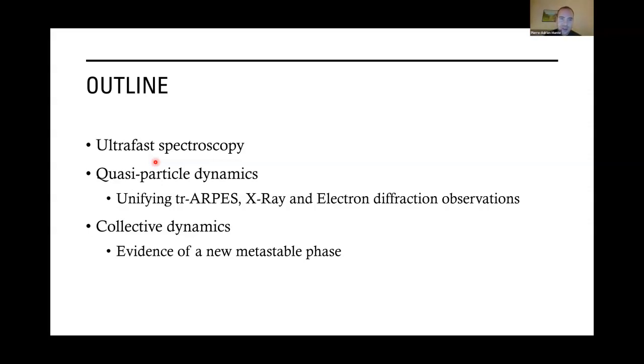And so in my presentation, I will first briefly, since most of you are well-versed in ultrafast techniques, just skim through the experimental setup we used. And then we performed experiments on the quasi-particle dynamics using ultrafast visible pump-probe spectroscopy, with the idea of trying to unify, since this material has been studied with really a lot of techniques, time-resolved ARPES, X-ray, electron diffraction, which can interrogate individually either the electronic system or the lattice system.